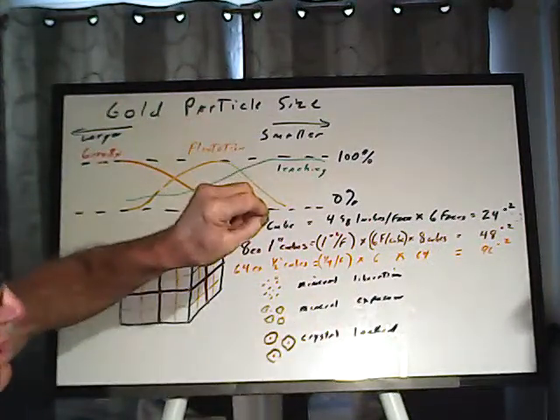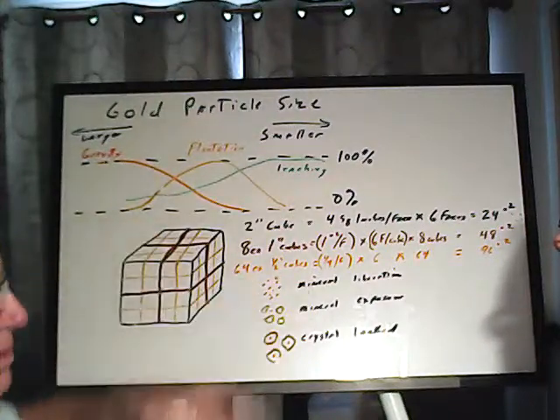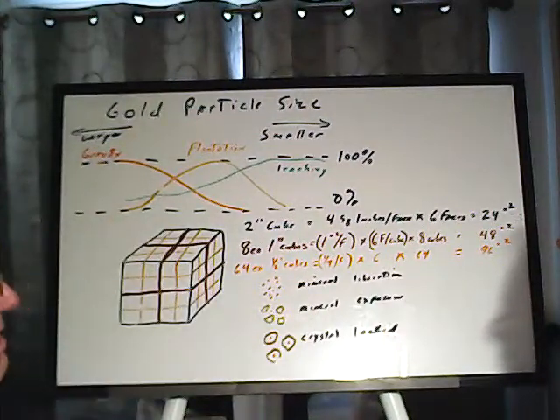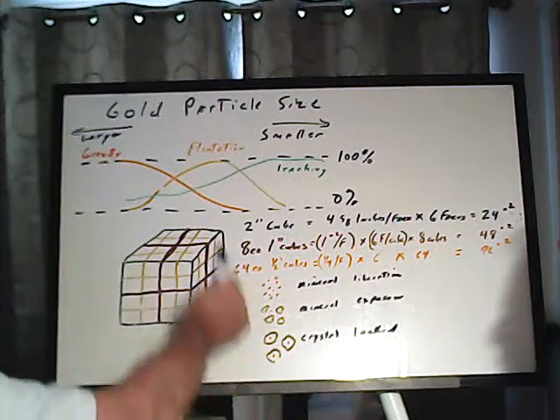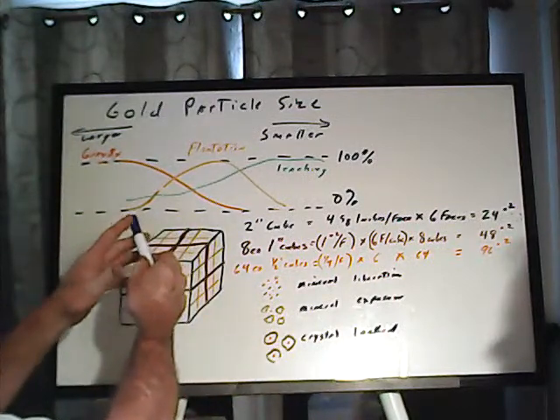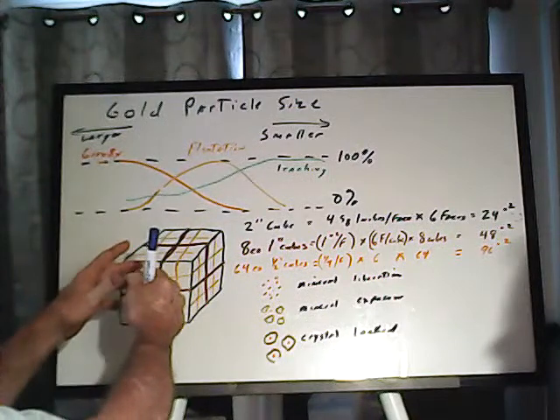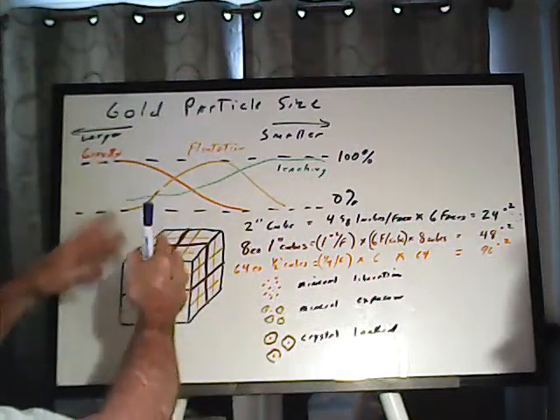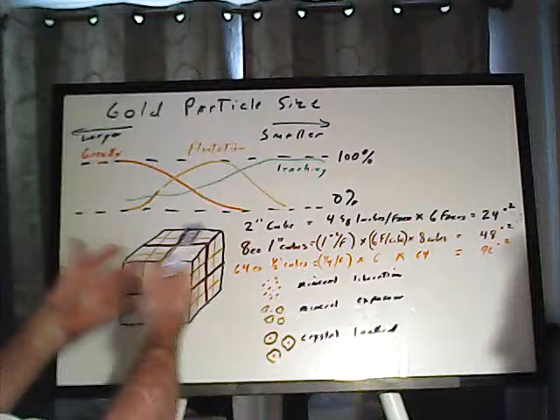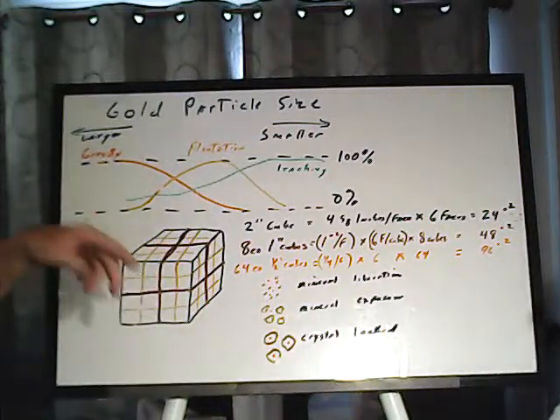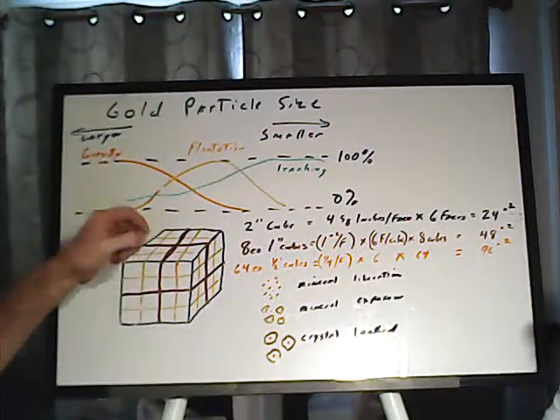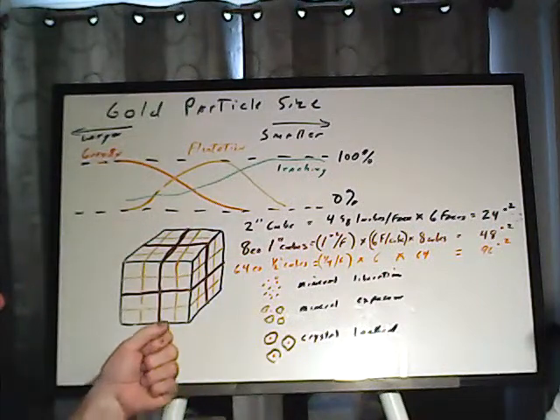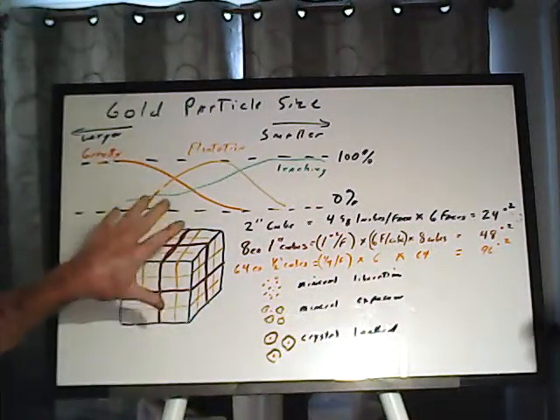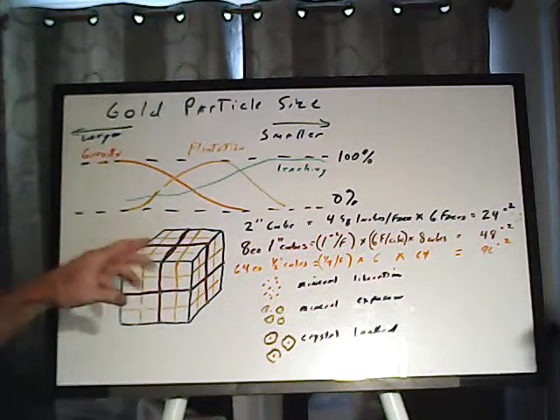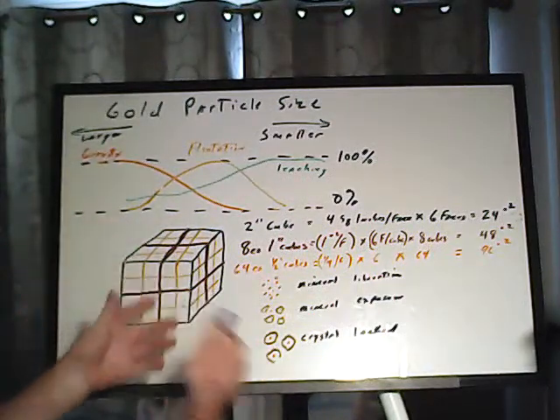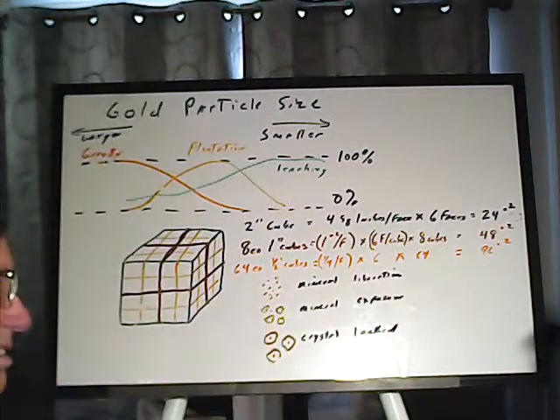As it gets real fine, it gets a lot more surface area. But there's another thing too. Many of these chemical reactions, when they're working on the surface, tend to leave a residue behind. And when that residue gets thick enough, it can no longer dissolve anymore. That's called passivation. You're passivating the surface. And as such, larger particles may become completely impossible to dissolve no matter how long you took.